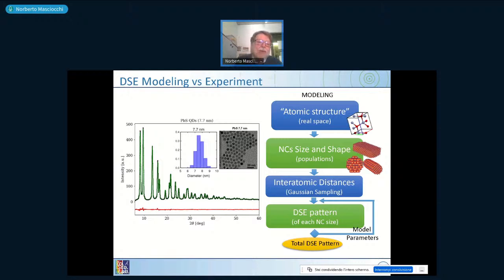So one main thing, why should we go to X-ray scattering if we can just count these materials? The reasons are many. One is that who tells us that the material in your imaging is all PbS and not something else? This is only given by the X-ray powder diffraction trace. The other thing is that by doing this histogram to the right, you are only having a very tiny portion of your system. You see the scale bar at the bottom is about 20 nanometers, so you are just imaging 100 by 100 nanometers. But your sample is like a few milligrams. So you are just sampling a very small portion, which has a very statistical weakness, because you're just imaging a small portion and everything else could be different.